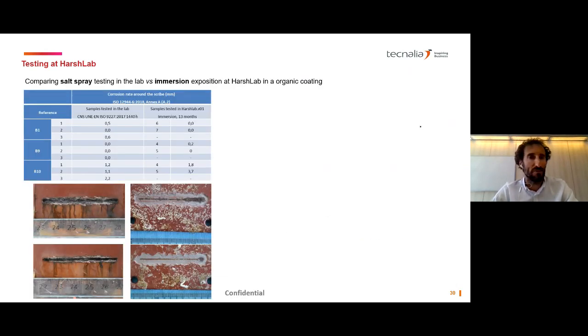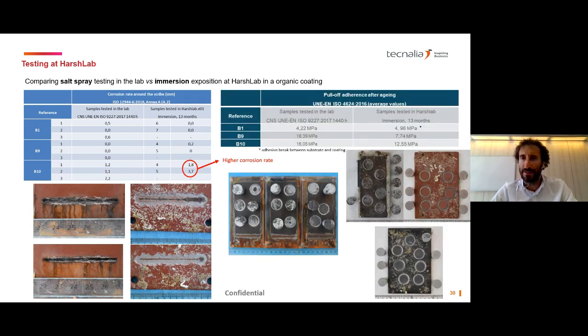So this is a very, very brief comparison between how samples behave in a salt spray test in the lab for 1,400 hours versus immersion exposition at HarshLab of organic coating. We can see here those pictures: on the left, in the lab after the testing, and on the right, the HarshLab specimens. We can observe quite higher corrosion rates in HarshLab in 13 months. And these are the tests of pull-off adherence after aging. Again, less tension, less force was needed